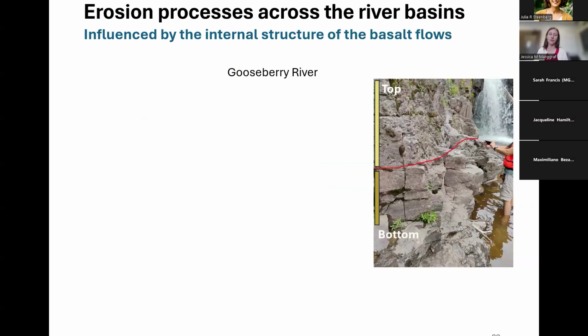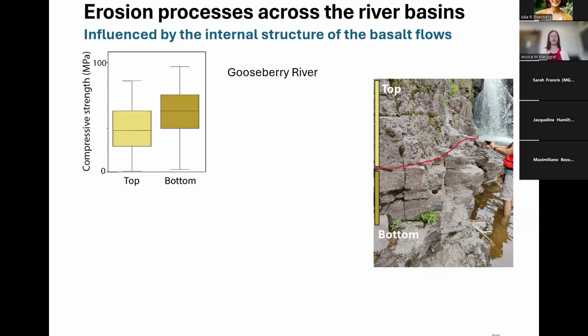And what is also nice about the Gooseberry, as we focus more on the erosion processes again, is that we can really see such a clear influence of the internal structure of the basalt flows. So here is an example from one of the vertical walls around the pools of the Gooseberry, like the lower falls. We see this distinction between the amygdaloidal top of the basalt flows and this much more massive, homogeneous center or bottom part of the basalt flows. You can also see some of these cooling fractures giving these basalt columns, the hexagonal columns. And between the top and the bottom of the flow, we see such a distinction as we can already expect in the compressive strength. So the massive bottom part is much harder, much more resistant than the amygdaloidal top part of the basalt flow.